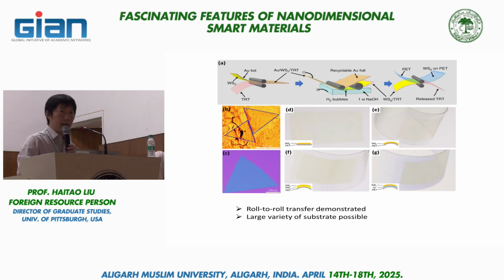And by doing that, you can create, if you look at the bottom right, there are four optical images, and they show a very faint yellowish structure in the middle of the plastic, and the whole structure is a piece of plastic sheet. And what you see is the transferred TMD onto those plastic sheets. And you can make sensors out of this flexible substrate, you can make electronic devices out of this flexible substrate, and so on and so forth.